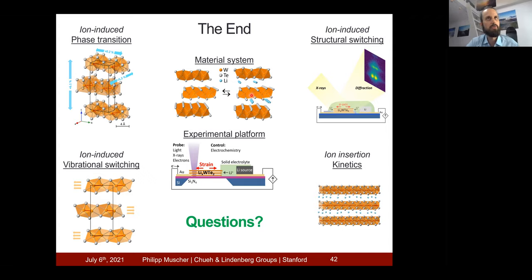Yeah, thanks for that question, Anudeep. With the technique of ultrafast electron diffraction, we would be able to pick up a change. It would have to be a dramatic frequency shift so that in the time frame that we measured and with the sampling rate that we used, it would not show up as an oscillation anymore. So it seems more likely that the excitation mechanism of that shear mode is actually broken due to lithium insertion. This is not a resonant excitation of the mode. We're using a high energy laser to excite this mode, so it's a special case that the mode can be excited outside of resonance. That's a special case in pristine tungsten ditelluride. So it seems more likely that lithium is disturbing that excitation mechanism. Does that make sense?